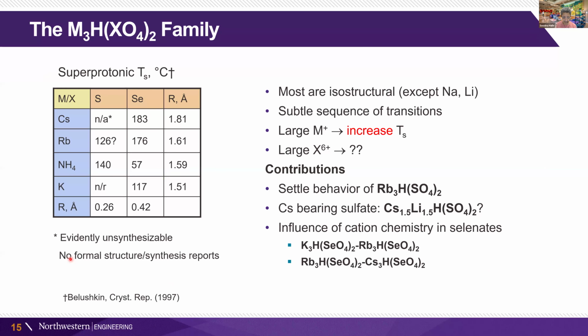So the overall view on these materials is that if we look at which materials have this transition, which don't, generally the increase in the cation size increases the transition temperature. It's not really clear what happens when you change between sulfur and selenium. And so we did some experiments in particular where we looked at the rubidium sulfate compound and found that it didn't actually have a superprotonic transition. So again, just making sure that we understand the material set overall to be able to draw design principles from what we know. And then we looked at the influence of the cation in the selenate system. So we looked at solid solutions between potassium and rubidium, and solid solutions between rubidium and cesium.